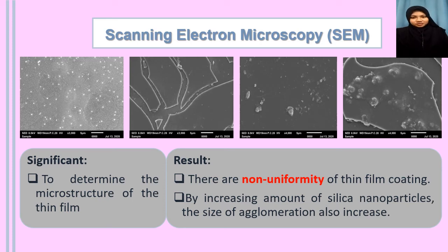For the third and the fourth picture, it shows that there is agglomeration inside the coating. It happened because the silica is not well dispersed inside the coating. So it can be said that there is non-uniformity of the thin film coating. And by observing the micrograph trend, by increasing the amount of silica nanoparticle, the size of agglomeration also increases. This agglomeration will affect the light scattering and will contribute to low transparency. To identify the mesopore structure, better analysis can be done, such as by using transmission electron microscopy, in order to identify and characterize the size of pores inside the coating.